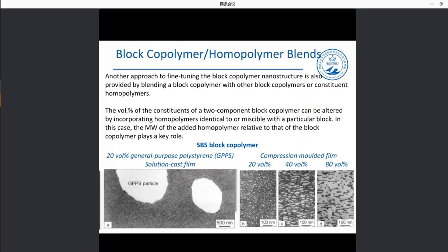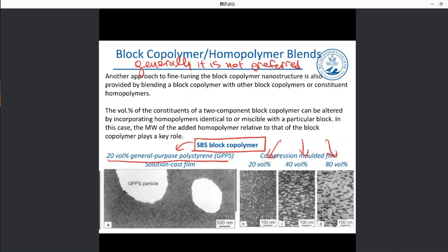I'll just use this example to make this a bit clearer. It's not that important. So we have a styrene butadiene block copolymer, and what we do is add 20% of polystyrene. By adding more weight of the polystyrene, essentially we create this structure. But again, this is not something perfect, so generally it is not preferred, because it is a kind of combination between copolymerization and blending. It creates not so ordered structures, and we lose the control that we have, and it can also create weak interfaces.